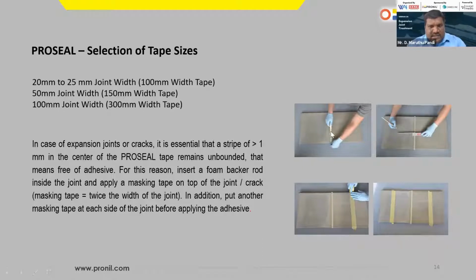Here you can see that the expansion joint was sealed with masking tape, so that other material does not get into it, and half a portion of this, if it is 20-25 mm, we need a 100 mm tape. So here he will be putting a masking tape to apply the epoxy adhesive.